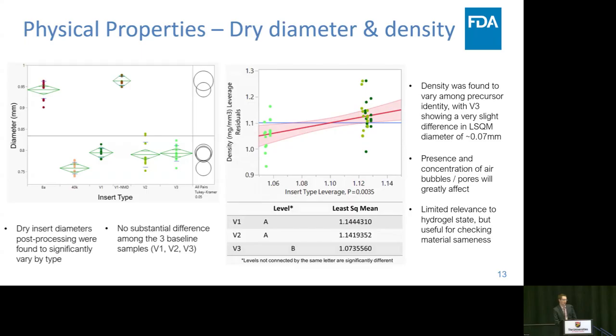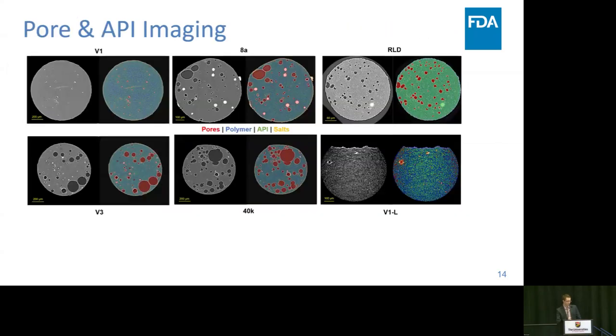And this kind of comes back to the rheology and what we learned from there, that the viscosity of the pre-cured mixtures is likely impacting the mixing dynamics and the propensity to have air bubbles and pores form. And this results in a different density in the bulk state.